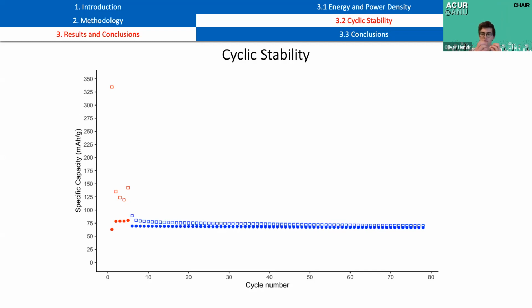And this means that some of your charges that were in the electrolyte are now trapped in this coating. And therefore, since capacity is a measure of the amount of charge that can move, it leads to an irreversible loss in capacity, is what people in the field call it. And so this will always happen when you first run the battery for the first 5 or so cycles. The capacity will decrease, and once that stable SEI layer has formed, then it'll kind of stay the same. Although you'd expect as the cycle number continues, often there's a decrease in capacity, but we haven't observed that to a great extent here.